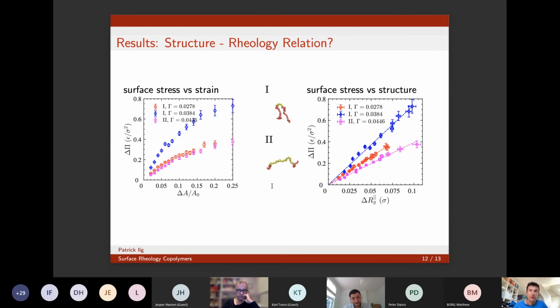One tiny first step that we did in this direction was trying to relate structure and rheology. On the left, you see the surface stress, which is the extra dilatational stress, versus the area change. On the very left, these are the linear response regime, very tiny deformations, and then up to 10 and 20% area change, which is quite in the nonlinear regime.